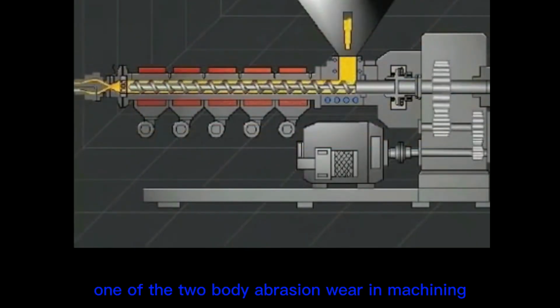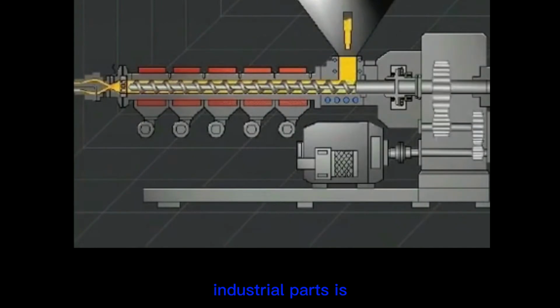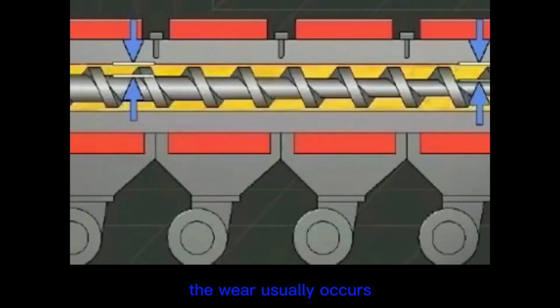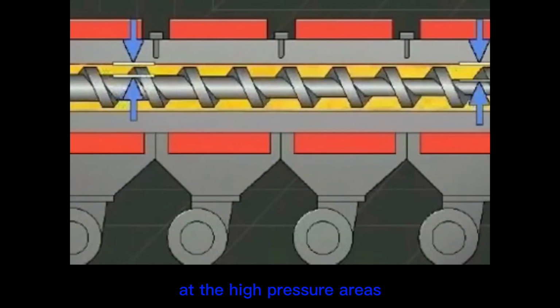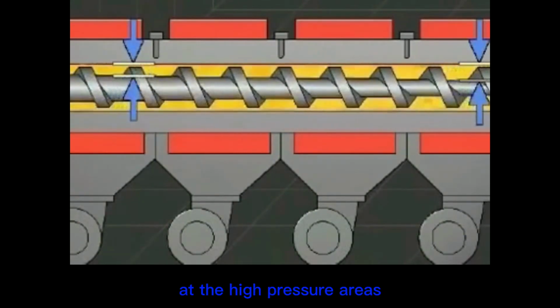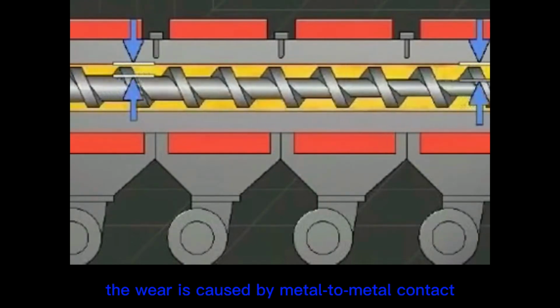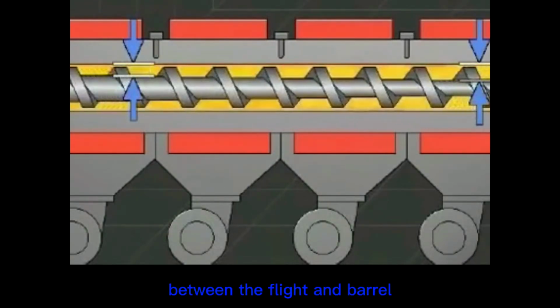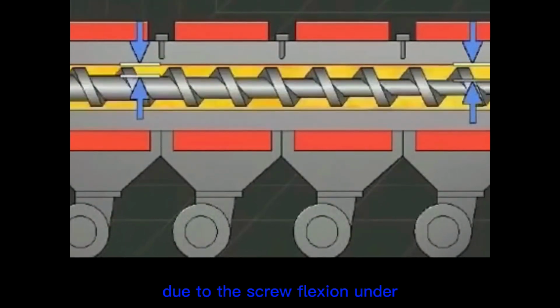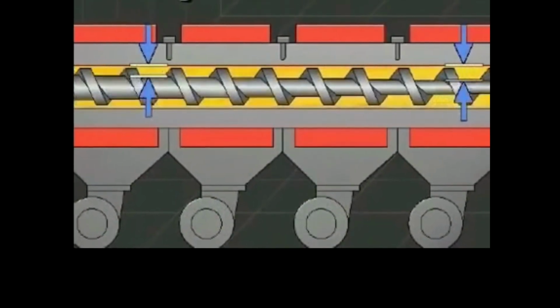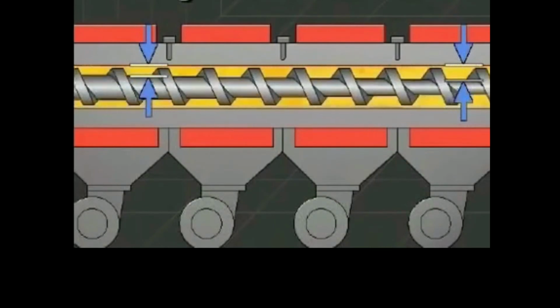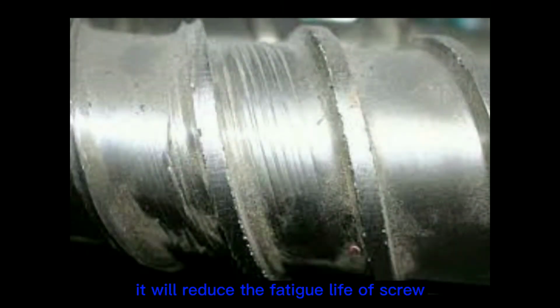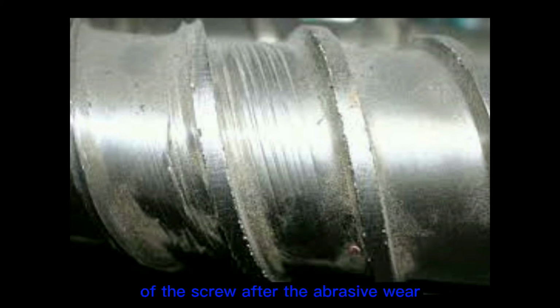One example of two-body abrasive wear in machining industrial parts is abrasive wear at extruders. The wear usually occurs at the high-pressure areas. The wear is caused by the metal-to-metal contact between the flights and barrels due to the screw flexion under these high pressures. It will reduce the fatigue life of the screw. This picture shows the condition of the screw after the abrasive wear.